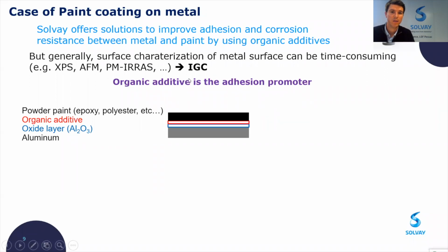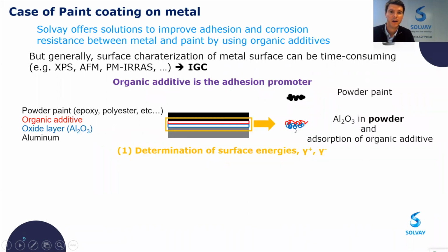So organic additive is the adhesion promoter. It makes the links between the powder paint and the aluminum and the oxide layer at the surface. And the idea here is to try to understand the interaction between the organic additive with the oxide layer. So for that, we put aluminum oxide in powder and adsorb some different amount of organic additive and measure the surface energy gamma plus and gamma minus. And we perform the same thing for the powder paints.